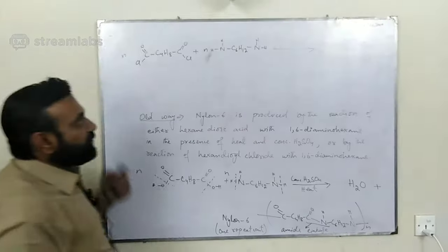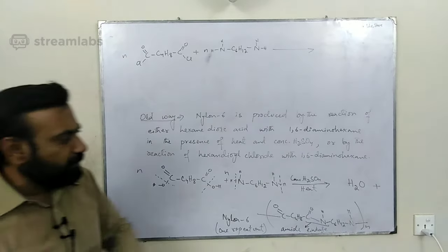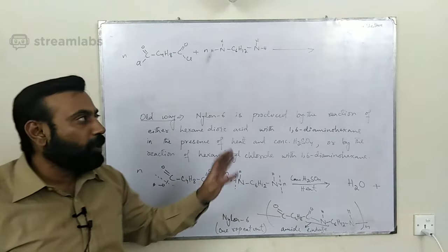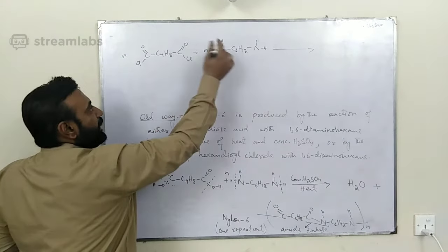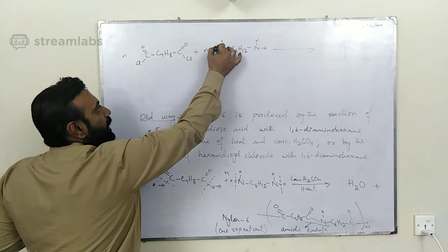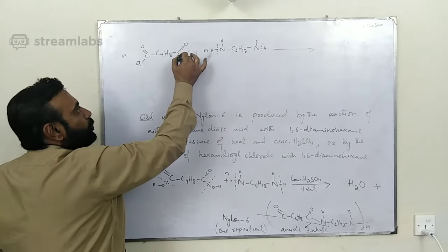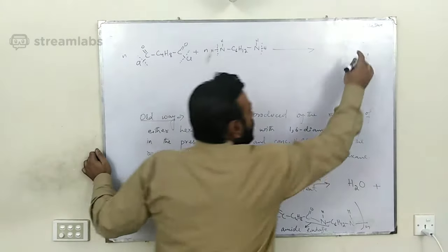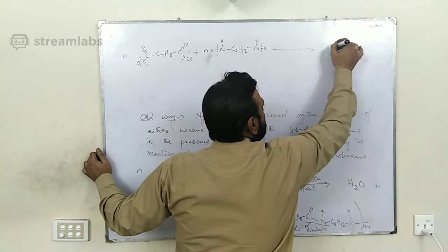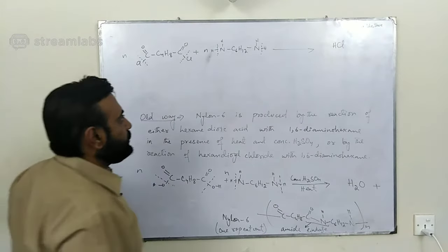This time a condensation reaction will take place between them without any specific conditions. We do not need to heat them, we do not need to use any catalyst. Just by mixing these monomers, amine groups will lose their hydrogens, whereas acyl chloride groups will lose their Cls, and those hydrogens and chlorines will link up to form HCl.